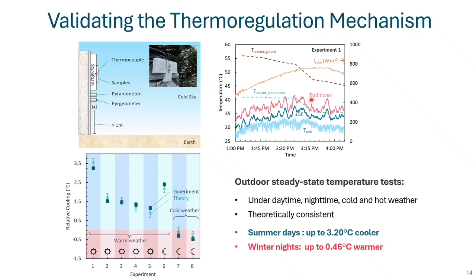Overall, we conducted 8 experiments under diverse weather conditions. The bottom graph shows the difference in steady-state temperature between the white paint and the directional emitter. In the first 6 experiments, conducted under warm weather, the directional emitter consistently outperformed the white paint, always being cooler by up to 3.2 degrees. However, in the last two experiments conducted in cold weather, the situation reverses. The directional emitter is now warmer than the white paint, up to half a degree.